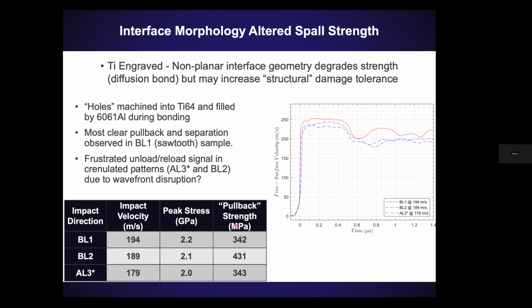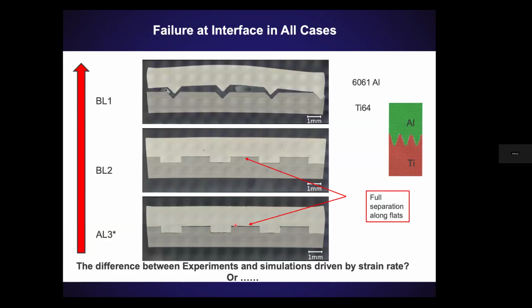But again, PDV is one diagnostic. When you look at the interfaces and how they fail, you notice that the flat interface was delaminating. Here in the pointy interface, it's basically coming apart at the interface completely. The interesting thing was that when you have the square interface, these vertical regions of the interface are staying together while the horizontal regions are coming apart. That was really interesting.